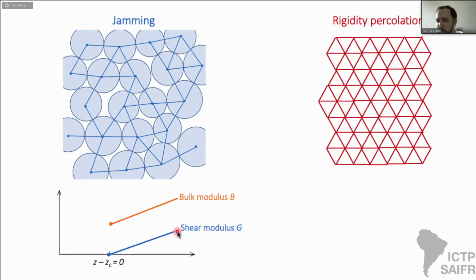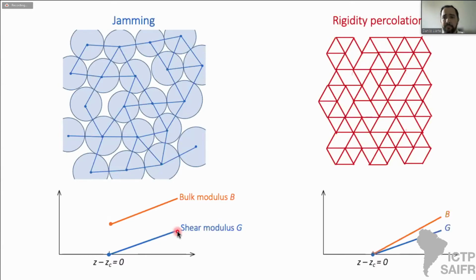Now there's another widespread framework to describe a transition to a disordered solid that's very similar to jamming. It's called rigidity percolation. In this case, one usually starts with a fully occupied network, such as the triangular lattice shown here, and then randomly removes bonds. And bonds for us will be just harmonic elastic interactions, or springs, if you like. And as you keep removing these springs, the average coordination number Z drops to ZC, and the system exhibits a transition from an elastic to a floppy phase. As in jamming, the transition happens at the same isostatic point, but now B and G vanish continuously at ZC. The difference and similarity between jamming and rigidity percolation leads to the inevitable question of whether or not it's possible to devise a unifying framework to describe both transitions.